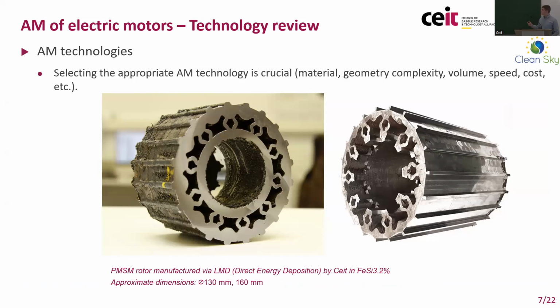In this example, what we are seeing is an electrical machine rotor concept manufactured by CEIT, using the laser metal deposition technique, which is a direct energy deposition technique. In this case, what you can see in the picture on the left is the processed part, in which just the front surface has been machined. Whereas the picture on the right is the part after being additively manufactured and machined in order to meet the final geometry.